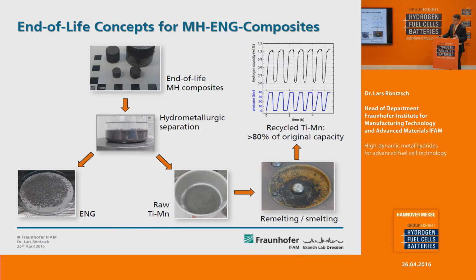Also, of course, important is always the question of recycling of materials. When we have reached the end of the life cycle, one has to think about recycling these materials, and hydride composites are much trickier than raw metal hydrides. You have a composite of different types of materials. We use hydrometallurgical separation, for example, and you can get to a secondary use material that from the first trial reaches 80% of the original capacity, basically the same kinetics, and the slide proves that it's really possible to recycle the material and thereby also save the environment.